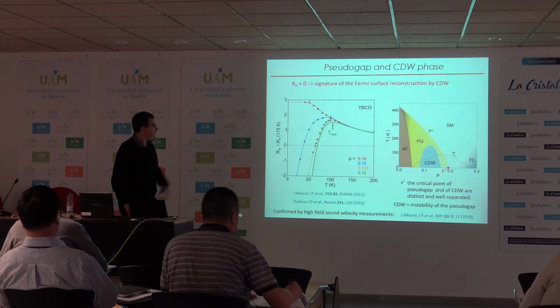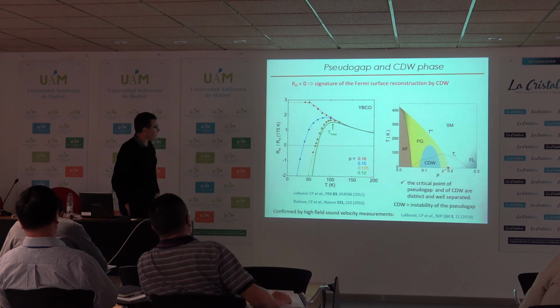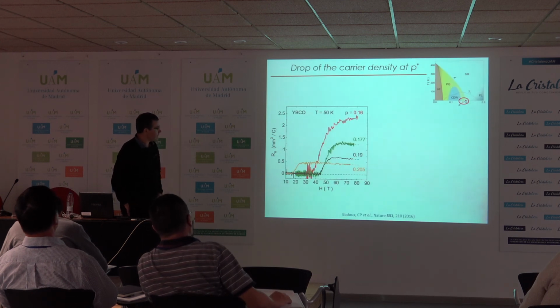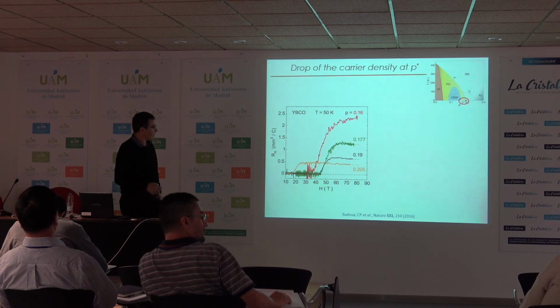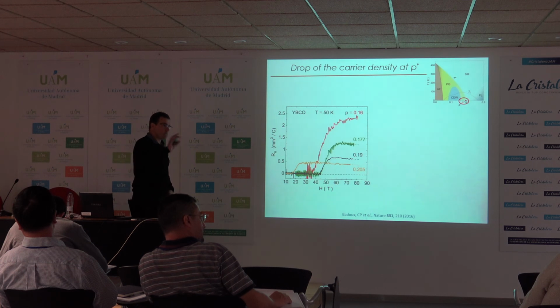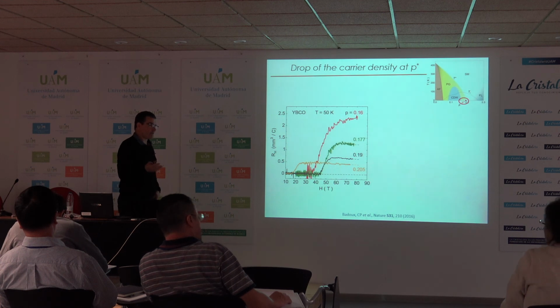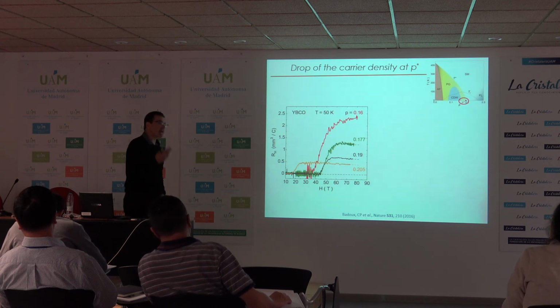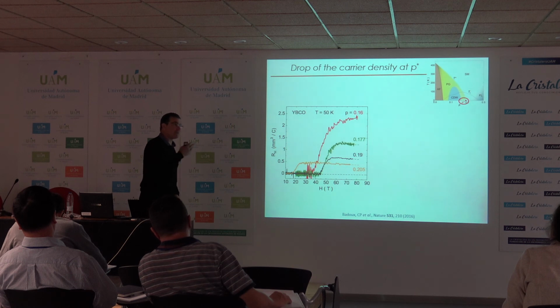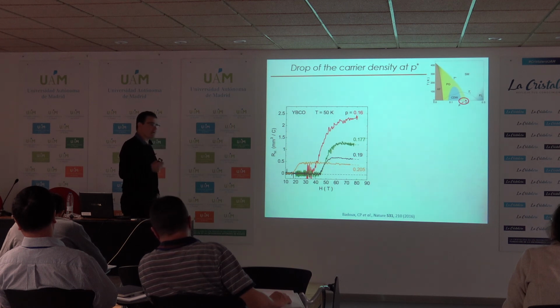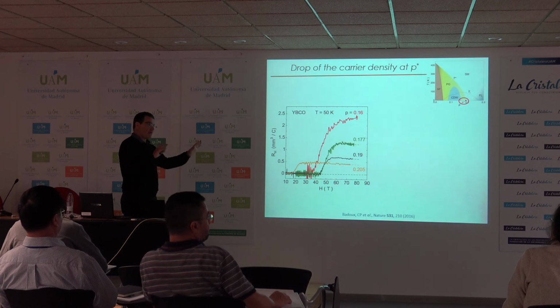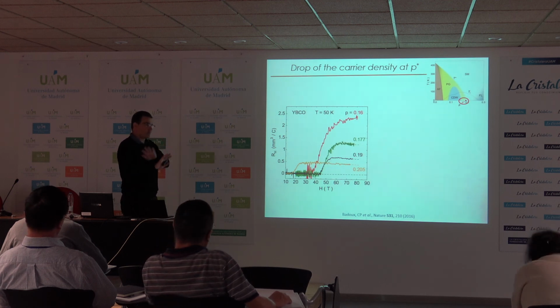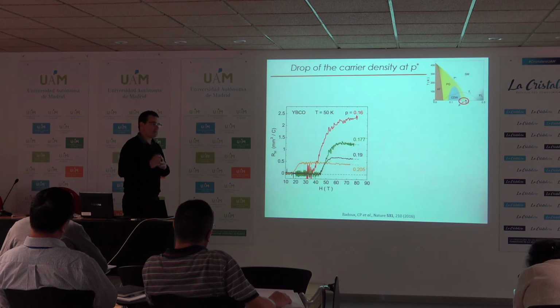Here I show only measurements down to 40 Kelvin, but for some doping we succeeded to go down to 20 Kelvin, and you see the Hall effect at low temperature remains positive. There is no sign of any curvature and negative Hall coefficient. This is not a direct proof, if you like, it's just a transport signature of the charge density wave. Charge density wave means reconstruction of the Fermi surface, meaning electron pockets. So this is how we measure.